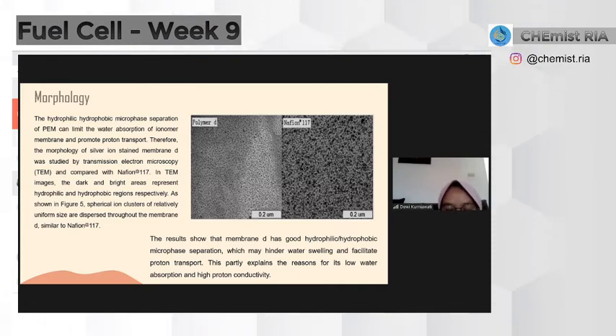As shown in figure 5, spherical ion clusters of relatively uniform size are dispersed throughout membrane D, similar to Nafion 117. The result shows that membrane D has good hydrophilic or hydrophobic microphase separation, which may hinder water swelling and facilitate proton transport. This partly explains the reason for its low water absorption and high proton conductivity.